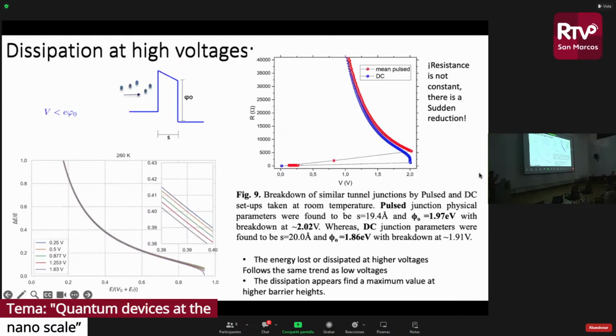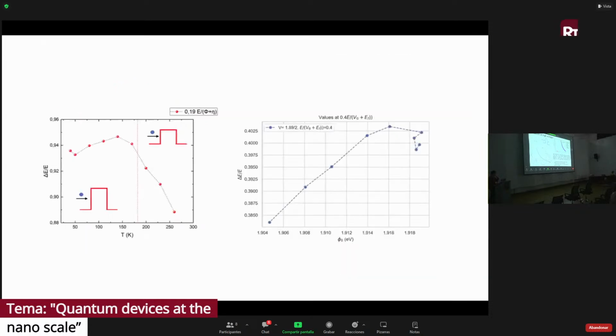Okay, this is also another important result. I will just mention the resistance of the junction as a function of voltage. You can see from the DC pulse method, there is a drop in the resistance, though it's not superconducting. However, the conductivity increases dramatically at high voltages for that junction, okay? What's the explanation? Basically, the barrier height is an important parameter. If the barrier height is a little bit smaller, then the dissipation is smaller. That was the main conclusion.